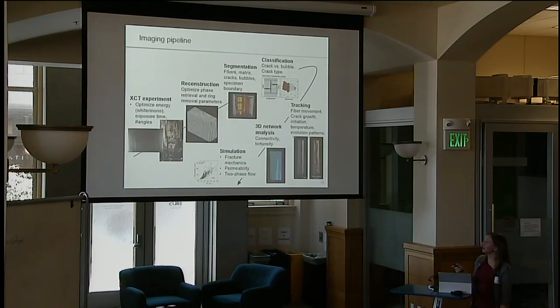So the imaging pipeline here is fairly similar to the last one, but there are a few different steps for what we want to get from this data. So first, again, we optimize the XCT experiment. We want to image quickly enough to see the cracks forming, but not so quickly that the image is too low quality. Then reconstruct the data, and then segment the fibers, the matrix, the cracks, the bubbles, and the specimen boundary. So with all of these different features, we can identify what types of cracks are forming, because this